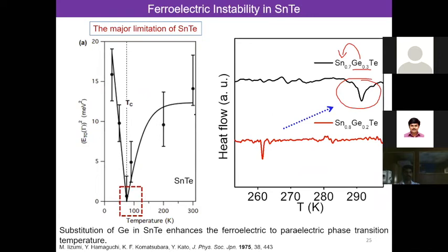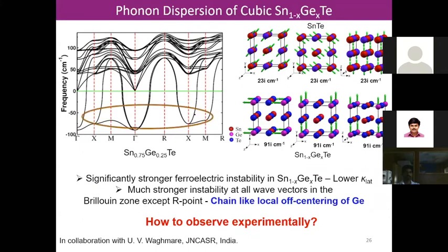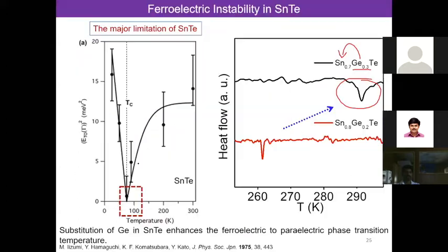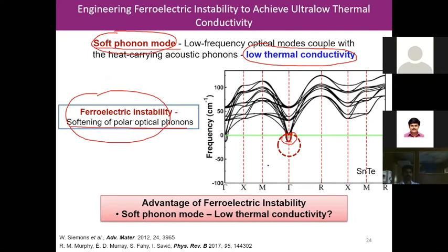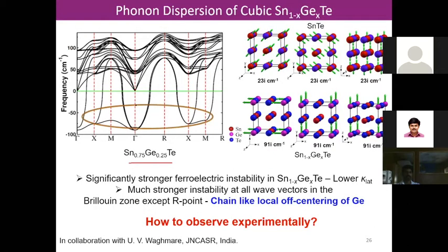Then in collaboration with Umesh we calculated the phonon dispersion, and this showed extremely significant phonon instability, which is the ferroelectric instability in this composition. See, the instability in pristine tin telluride is small, whereas the instability in germanium tin telluride is extremely high. If you do this analysis here, we see the instability at all points in the Brillouin zone except the R point.